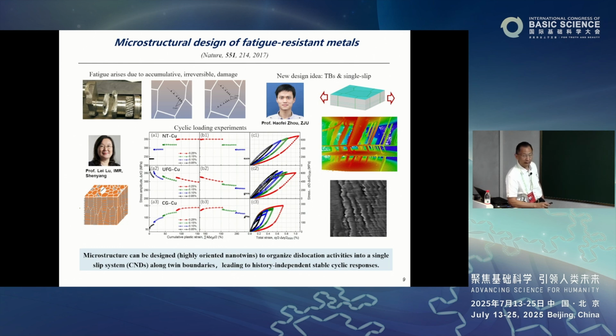Right. So far, there has been very little progress in this field. But we understand how fatigue happens. Fatigue is because these microscopic, atomic defects in the material start accumulating and pile up against boundaries, grain boundaries, or they pile up against each other. They have a cross slip. You have this defect, they pile up against a cross section. These intersection points become sites of high stress concentration. They develop cracks. That's how material develops these defects and then cracks, the micro crack, then eventually fails. Right.